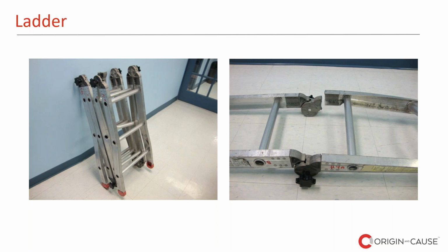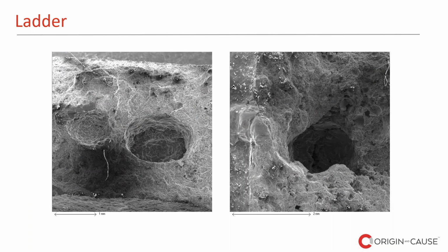We were retained to provide an investigation. We put the parties together. We provided a testing protocol, and we conducted a joint destructive examination. That hinge was cut in smaller pieces to fit under the microscope. And again, we took it under the scanning electron microscope to see the features on the fracture surface. And as you can see here, there is a lot of porosity in that hinge. So that hinge's load carrying capability was drastically reduced by manufacturing deficiencies. So at the end of the day, it was determined that it was the foundry that cast that hinge responsible for the incident.